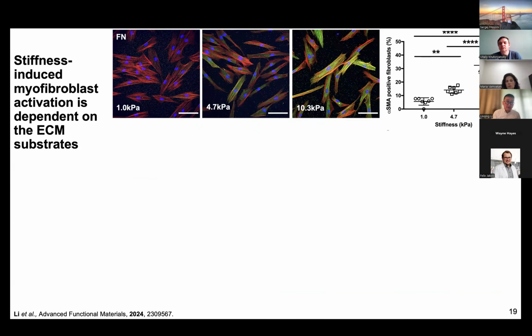To further demonstrate how we can tune the ECM proteins, the biochemical signaling and the physical properties, we do these myofibroblast activation studies, which are known to depend mostly on the substrate stiffness. So we culture fibroblasts on a variety of different stiffnesses and a variety of different ECM coated surfaces. As we coat fibronectin on the surfaces and grow the fibroblasts, as you increase the stiffness, you see the green signal, which is smooth muscle actin positive fibroblasts, indicating the onset of fibrosis. So you can see the direct correlation: as you increase the stiffness, a greater percentage of the cells are activated as SMA positive cells, which has been demonstrated in other papers.